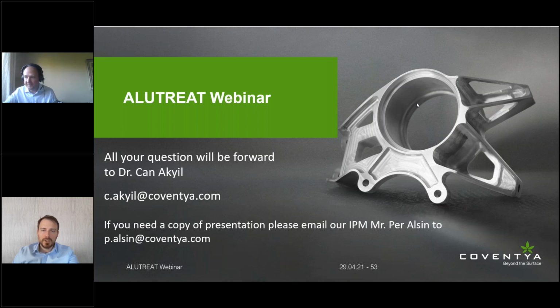Well, that's something that we will need to check, because generally speaking, a zinc concentration of maybe 0.5 to 1 gram would start causing problems. But generally speaking, the deox is not as aggressive on zinc-containing parts. The general principle with our customers is that they etch the surface much less, just removing the inherent oxide on the surface prior to powder coating. The dissolved zinc does not increase exponentially like aluminum does, where at least 1 or 2 grams per square decimeter is needed as an etch.